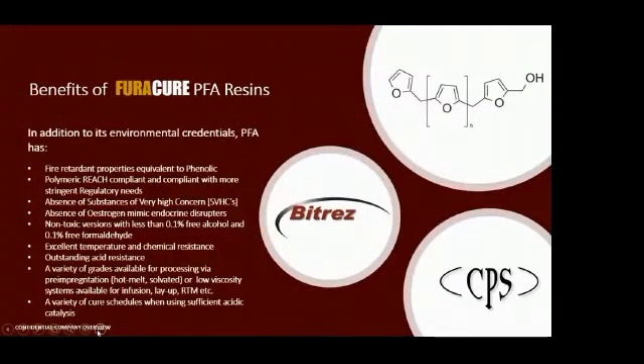Moving on to the benefits of the innovation, aside from the environmental credentials, the PFA resins offer the same flame retardant performance as a phenolic. These materials are polymeric, and so they are REACH compliant. They have an absence of substances of high concern, unlike traditional phenolics where we have phenol and formaldehyde. And of course, formaldehyde is a very dangerous substance if inhaled. We are able to replicate the performance of phenolics without the formaldehyde. And whilst the furfuryl alcohol is again a toxic material, we're driving those contents down to less than the threshold of 0.1% free alcohol. Very good temperature and chemical resistance and outstanding acid resistance.